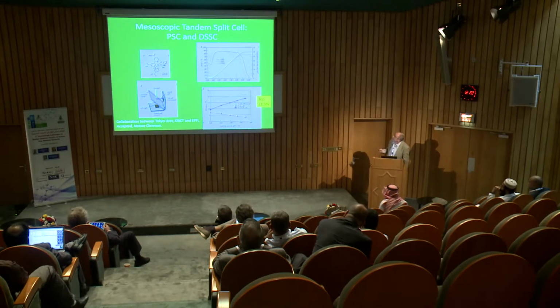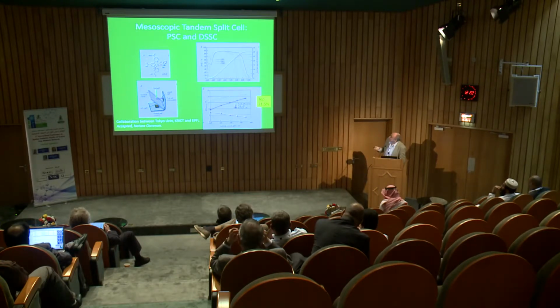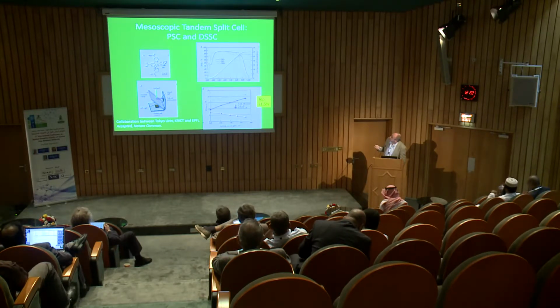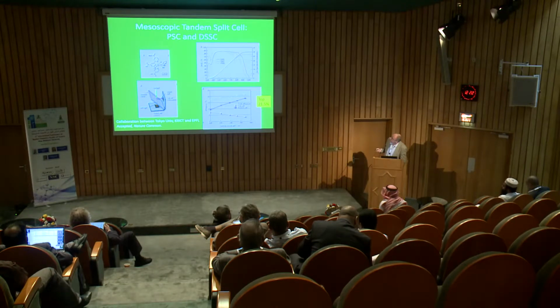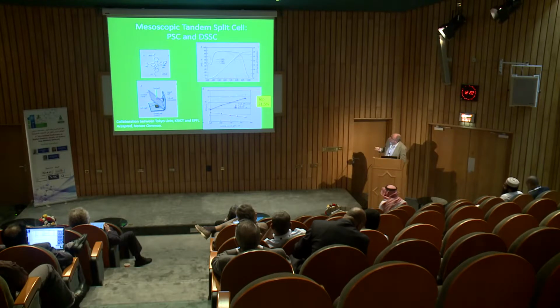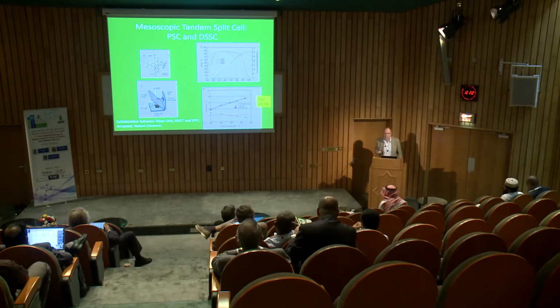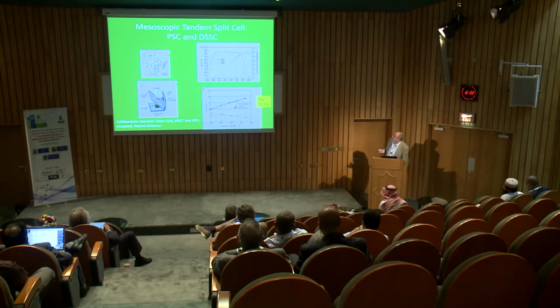We have another tandem configuration done with Professor Segawa in Tokyo. That is to take a dye-sensitized cell with our new black dye, they call DX3, as a top cell. It has an infrared absorption. You combine that with a perovskite solar cell, and then we do it not as nice as a monolithic. We have a split cell, so we take a mirror to split part of the spectrum to the dye cell and part of the spectrum to the perovskite. And as a proof of concept, we have 21.5% just published in Nature Communications.